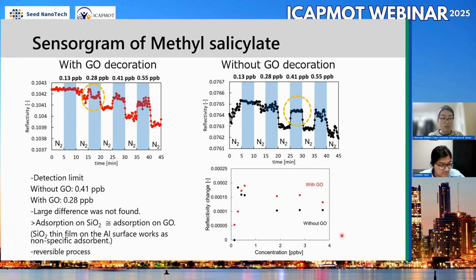So you can see that a large difference was not found between the two sensor types. That means adsorption on SiO2 is comparable to graphene oxide. So please note that the SiO2 thin film on the aluminum surface works as a non-specific adsorbent. So the adsorption of SiO2 is comparable to that on graphene oxide. Of course, this adsorption and desorption process is reversible. So yeah, we can use the sensor many times.